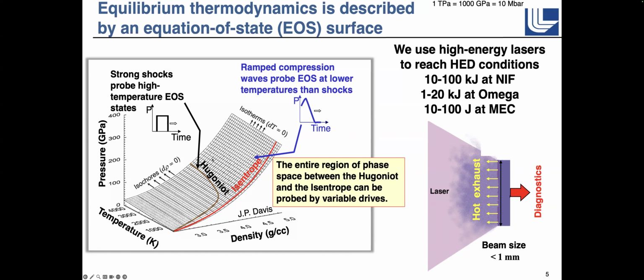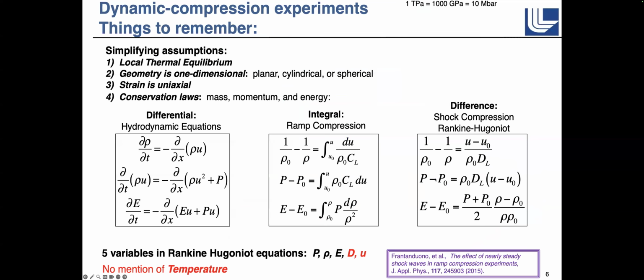The other good thing about that is that when you shine a laser on and form this plasma, you get a lot of X-rays coming out. And lower Z materials have lower energy X-rays, which are easier to block, easier to filter out, and so you get less preheat in your sample. And the size of the lasers is quite large. NIF is a 2 megajoule laser, and we generally use between 10 and maybe 300 or 400 kilojoules at NIF. At Omega, generally up to about 20 kilojoules, and at the XFELs, right now our biggest laser is at MEC, Matter in Extreme Conditions, at LCLS at Stanford, and that's 100 joules. And so I'll go a little bit more into that in a bit.